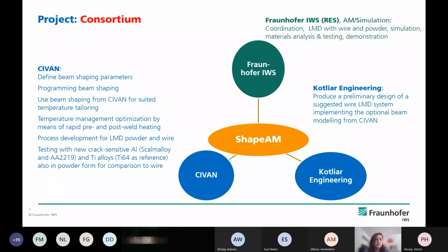Civan will scope the possibility of using their beam shaping technology, the laser beam sources, for use in additive manufacturing, and will support us in defining parameters, with the programming, and with this 3D temperature tailoring. And they will also test with us these new crack-sensitive alloys. So we schedule some alloys that are now in the community quite relevant, like Scalmalloy or AA2219. Those of you working in aerospace would know these alloys, and titanium 6-4 as reference.